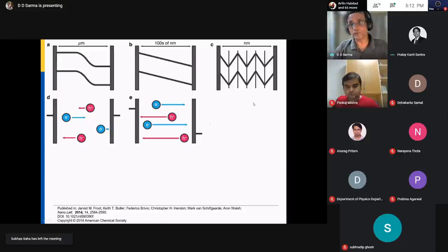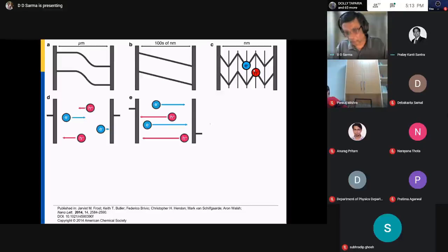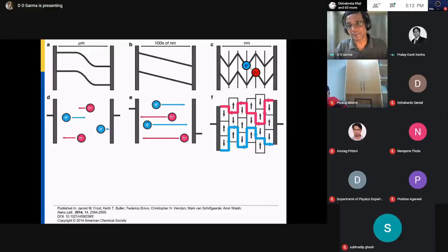And each of these domains will act independently. Now, wherever in this domain you create a charge, what will happen? The hole will go there, electron will go there. If you create it in this place or in this place, away from the electrodes, hole will come here, electron will go there. So basically, it doesn't matter in which domain you create it, immediately it goes to the two ends of the domain. So each domain now separates. Now think of the different domains of a ferroelectric material. Each domain is much shorter than the electrode dimension or the separation. But the pathways now are completely non-crossing. And so it gives rise to better efficiency of collection. Okay. That is the reason.